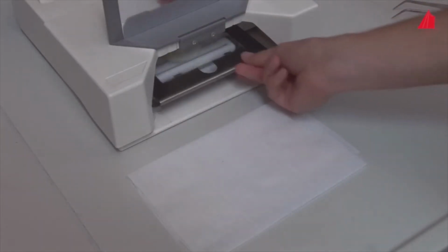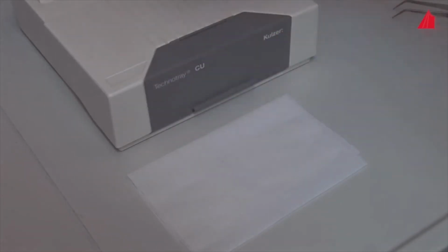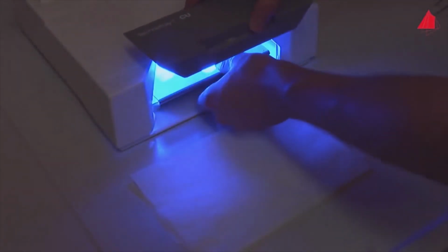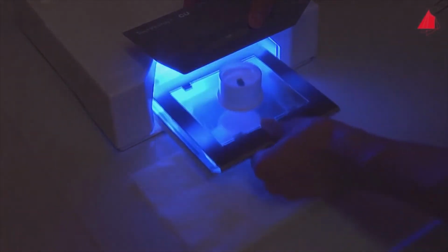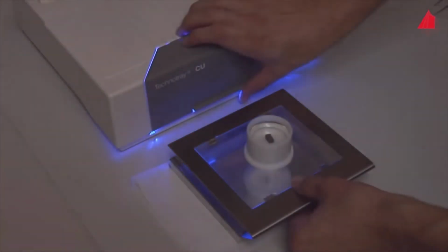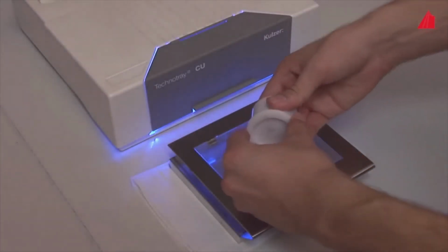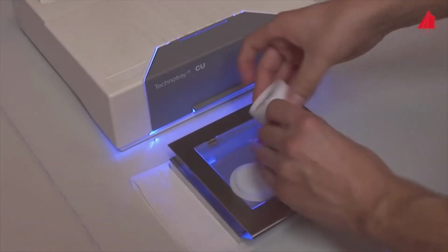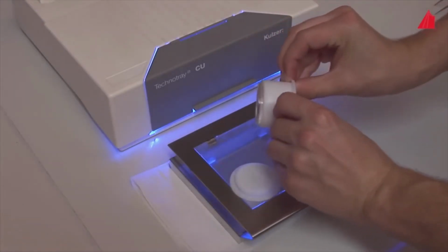Now the mold containing the specimen goes into the light curing unit. Under the action of intense blue light, the resin polymerizes within half an hour. The resin has cured and embedded the specimen well. As an alternative to light-curing resins, many other embedding materials are available. Each of them has its own advantages and disadvantages.